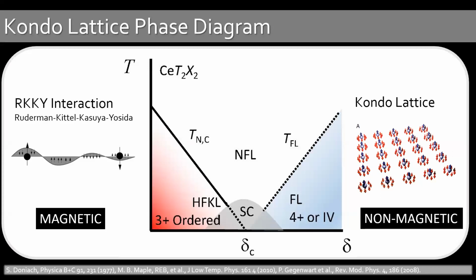There's this well-discussed and established Kondo lattice phase diagram where there's all sorts of interactions, but an extremely simplified perspective on it is that there's two that really matter a lot, and those are the RKKY interaction and the Kondo lattice interaction, right? So RKKY is this sinusoidally modulated polarization of the conduction electrons. And then you have your F elements, and depending on where you put them, you can have an antiferromagnetic exchange, a ferromagnetic exchange, or maybe even no exchange at all. In any case, this is one that favors a magnetically ordered ground state, and that's illustrated over here.